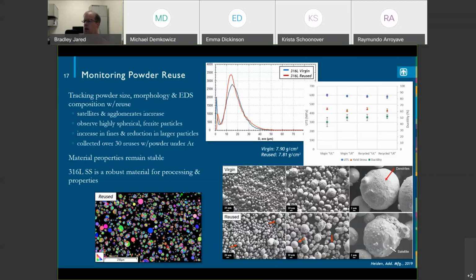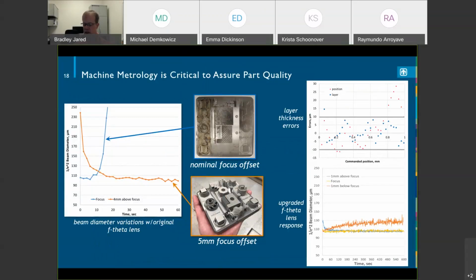Another piece of this is actually understanding the machine system itself. This was some work we did on our ProX. And so sort of the image on the left shows some issues we had. Actually, we had a thermal lens effect. So basically what happened was our 100-watt laser, our 1070 nanometer laser, was heating up the focal optic, the F-theta lens in the front of the machine. And what was happening is that we were losing focus. So after about 10 seconds, essentially our process conditions were changing quite dramatically. And so we couldn't actually build material.